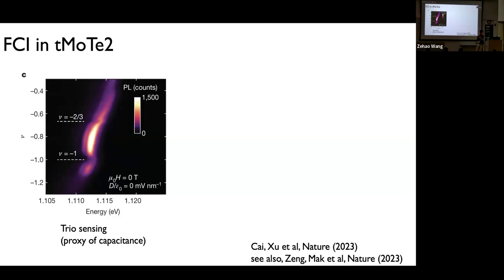it's taken as a proxy for the capacitance or the dielectric environment. So whenever you see some discontinuity, people think that I must have gone from a compressible state to an incompressible state, and this preliminary measurement already tells you that you have something interesting happening at 1 electron, 1 hole, and then 2/3.